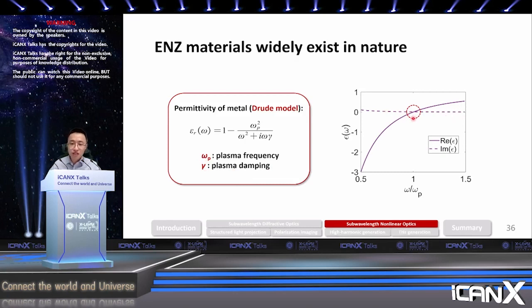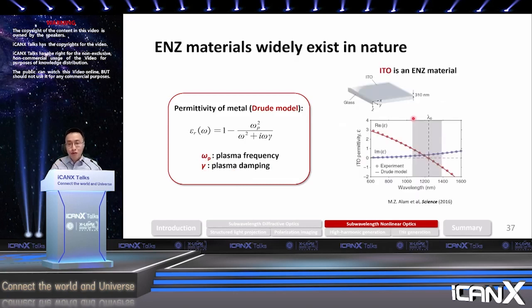Okay. To give you an example, one of the very commonly seen materials is this ITO, which is basically used for your transparent conducting electrode, also in your iPhone. Okay. So ITO basically is a conductive metal oxide that, with its permittivity, also can be governed by this Drude model. Okay. You'll see that for ITO, its permittivity will cross 0 somewhere in the near infrared range.